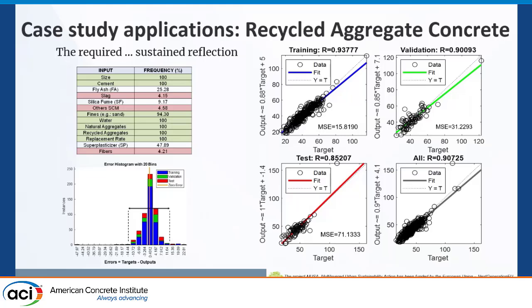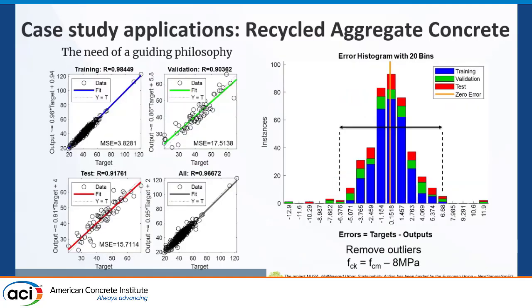So, simply said, let's try to remove them, and the error was greatly reduced: we went from 25 to 14, a little bit less. Then you can rely upon the removal of the outliers, and we ended up with an error which we deemed acceptable, below 7 megapascal. But why did we deem that acceptable? That brings us back to the human tool. Because, for example, when you look at the structural design codes, there is a rule of thumb that to go from the average strength to the characteristic strength, you subtract 8 megapascal. So that is some variability that we do accept in our current concrete technology production. So we deemed this prediction acceptable.